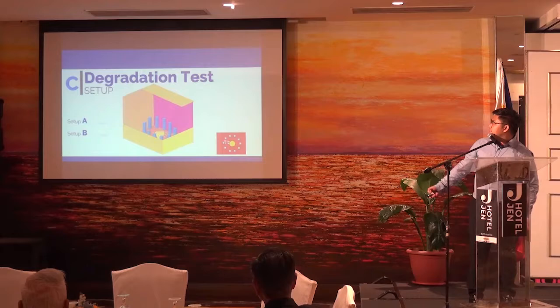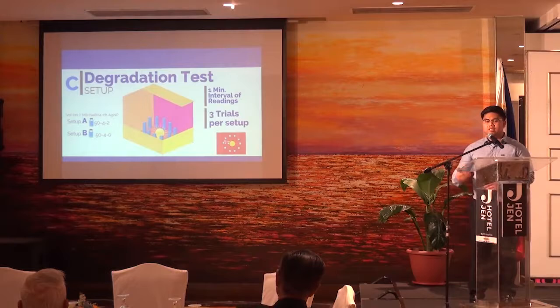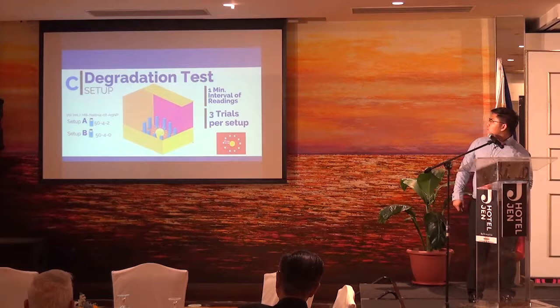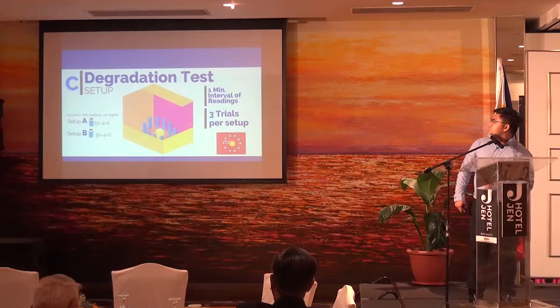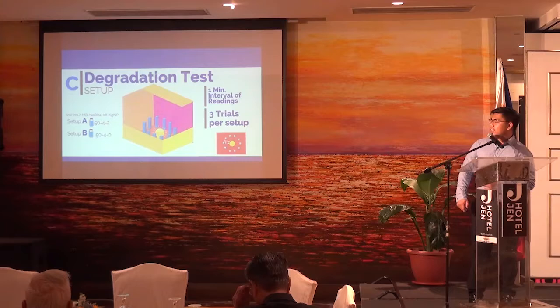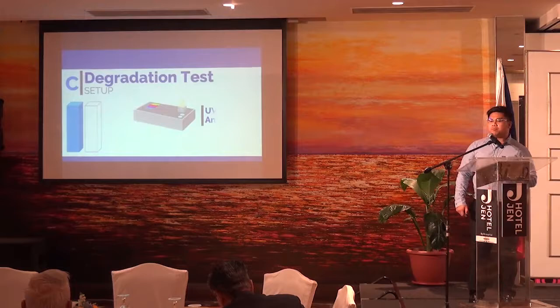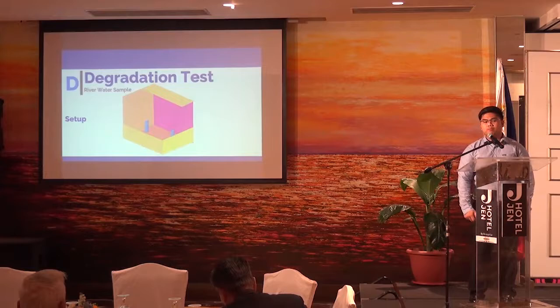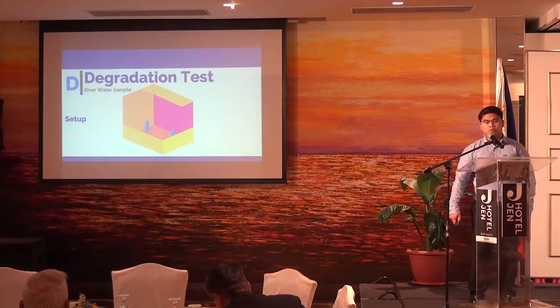Next is the degradation test. I used a box filled with a light at the center. There were three vials filled with two different types of solutions. The first setup consists of 50 ml of methylene blue added with sodium borohydride as the reducing agent, and the next reagent is our catalyst. Setup A has the catalyst and setup B has no catalyst, in order to verify whether our catalyst works. There were three trials, and every one-minute interval a vial is drawn out from the box and tested for absorbance. Next is the degradation test on actual real water samples, using the same method but with a river water sample instead of distilled water.